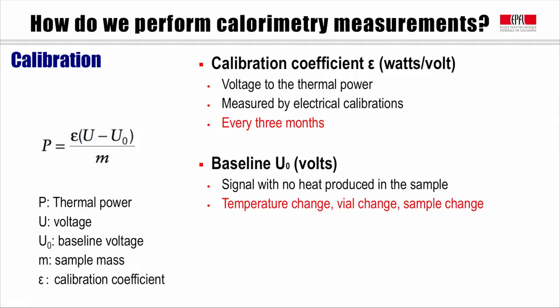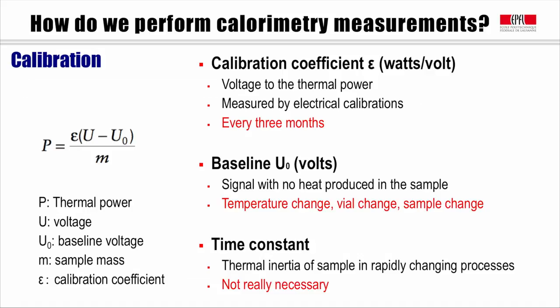There is another calibration called time constant, which is typically 100 to 1000 seconds. This calibration is not necessary for cement hydration since the time scale of cement hydration is much longer than this time constant.